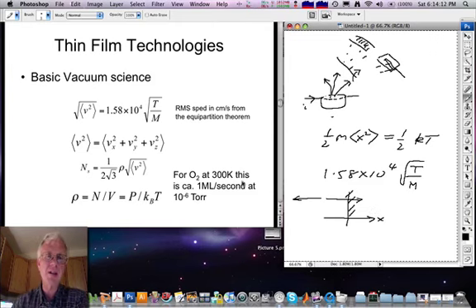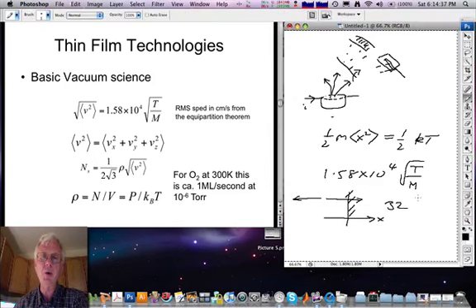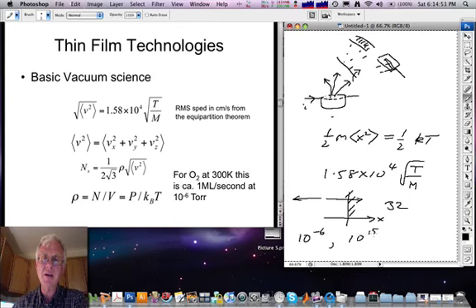In this equation here, rho is the density of the gas, but we can replace it with the pressure using the ideal gas law. If we say that rho is the number of particles divided by the volume, then this is equal to p divided by kT. This number can be worked out, and in the book we do it for the mass of oxygen, which has an atomic mass of 32. By substituting into this equation, we find that at a pressure of 10 to the minus 6 torr, so that's inserting p in place of rho in this equation, we get 10 to the 15 oxygen molecules hitting a square centimeter per second.